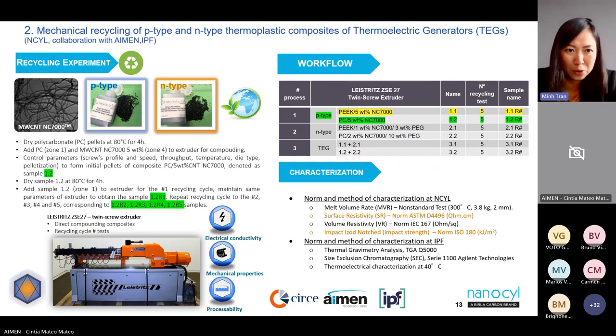For the recycling experiment, we also used the industrial pilot compounder line, and we performed 5 cycles of recycling. We worked with polycarbonate and PEEK, and later performed a lot of characterization on the samples to find out how the properties change before and after the recycling process. We measured, for example, the melt volume rate, the resistivity of bulk, surface and volume, the mechanical impact test, TGA, and also measured the thermoelectric properties at IPF. Next slide, please.